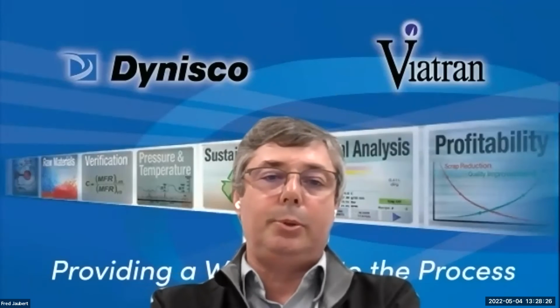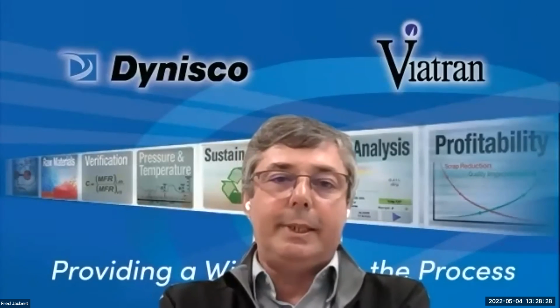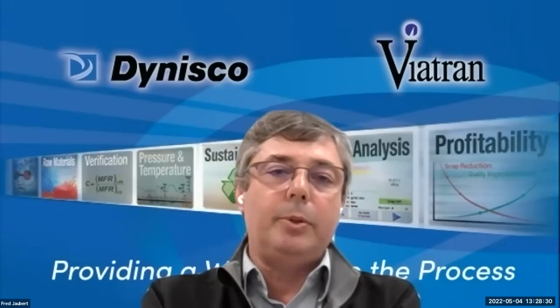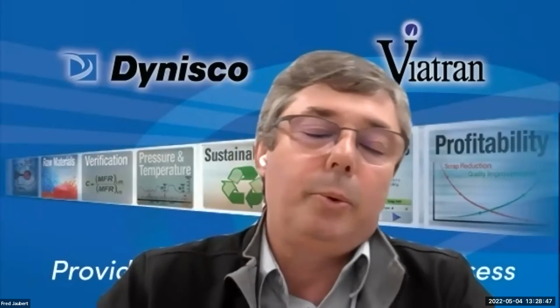So there are a lot of different applications. For example, we have right now an application at a customer who is doing polypropylene recycling, and they want to increase the melt index, so decrease the viscosity, and they are using peroxide to do this. And with our instrument, which is just connected at the end of the extruder, we have been able to control the level of peroxide so that they can get quite a constant melt flow index at the end of the extruder.